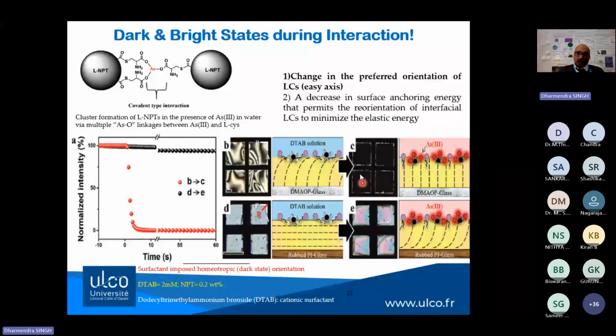So, okay, to confirm which mechanism is really responsible for that, we have repeated the same experiment. However, here instead of using DMOAP glass, we have used rubbed PI glasses. So basically PI is the polyimide layer, a polymer which orients liquid crystal in a planar or homeotropic manner. So here we have taken the planar orientation of the liquid crystal molecule, and look here at the D-type liquid crystal interface, and only the planar orientation is observed.